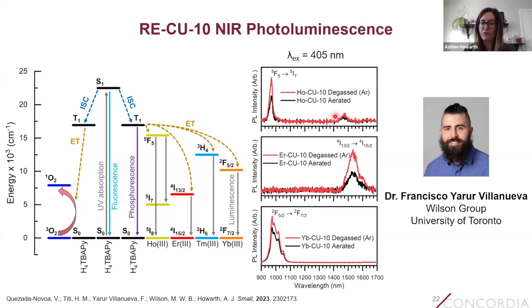We didn't see any emission for thulium, but that's expected, as thulium is very well known to undergo cross-relaxation processes, which quenches the metal-based emission. But we could assume that the energy transfer is likely taking place in this MOF as well.